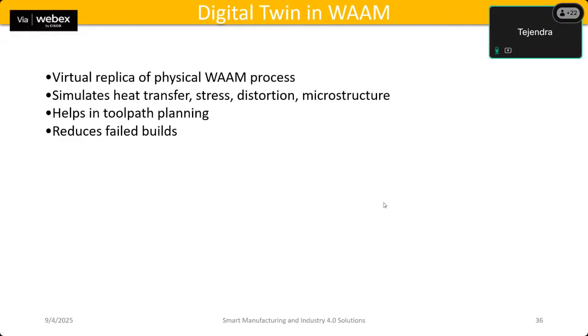We can know in advance what kind of grain structure or mechanical properties will result from a certain process path. The digital twin is also very important in tool path planning, as instead of experimenting on the machine, we can optimize the path of a robotic torch virtually to minimize the defects as well as the distortion. The biggest benefit is reduced failed builds. Since we already know how the process will behave, we can save both material and time by reducing the trial and error in the process. So basically the digital twin acts as a testing ground where the mistakes can be made virtually, not physically, making the wire arc manufacturing process the most cost effective as well as the most reliable process.